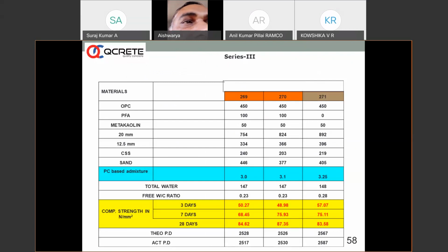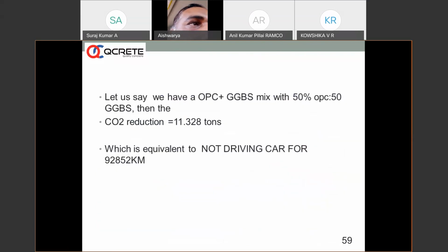Another example where OPC, PFA and metakaolin have given high strengths. As I said earlier, the M100 concrete in Burj Khalifa is done with a combination of OPC, PFA and microsilica. So if you are doing about 100 meter cube of OPC GGBS concrete with 50% OPC and 50% GGBS, carbon dioxide reduction is about 11.328 tons, which is equal to not driving a car for 92,000 kilometers approximately.